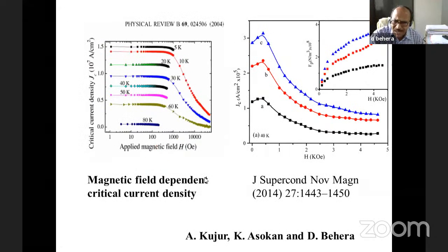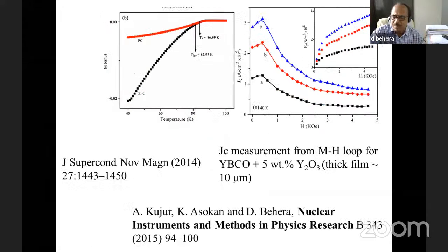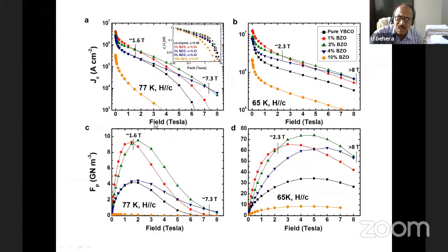If you measure the field-dependent critical current density, you see the critical current density increases by creating nano defects in your material. That means you can enhance the critical current density of the material by creating nano defects. These are different materials, that's all. So you can modify these materials by ion irradiation. This is a beautiful thing that you see here.